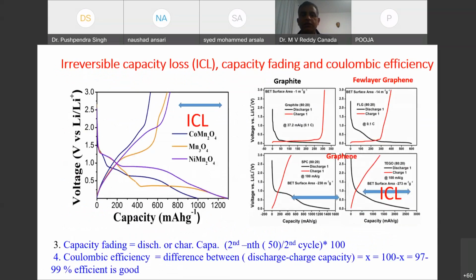And then irreversible capacity is very important. That's why during the first charge-discharge, you have to get a minimal value. These are some examples. A higher ICL is not good. For example, graphite has a lower ICL when compared to graphene, or materials with higher surface area. Although we can claim this type of material, it may not be really good for practical applications.